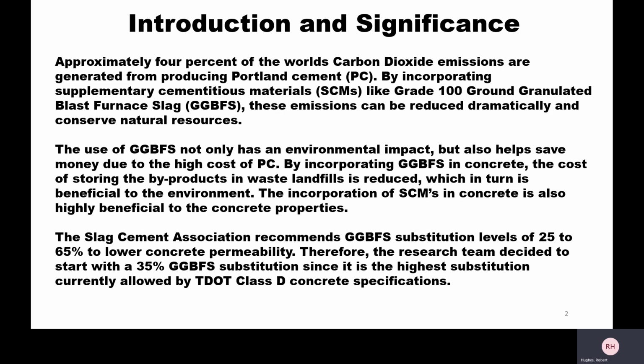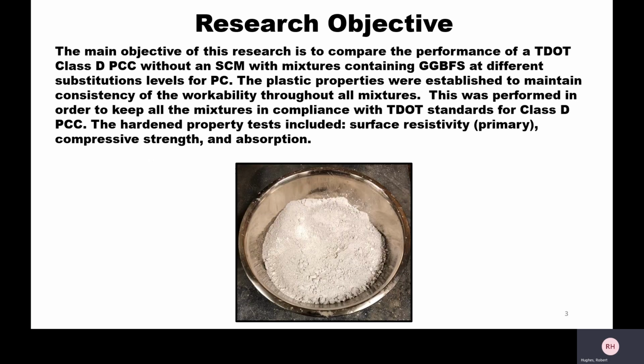Knowing this, the research team decided to start with a 35% substitution, since it's the highest substitution currently allowed by TDOT Class D concrete specs. The main objective of this research is to compare the performance of a TDOT Class D concrete without an SCM to mixtures containing GGBFS at different substitution levels for Portland cement. The plastic properties were established to maintain consistency of the workability throughout all these mixes. This was performed in order to keep all the mixes in compliance with TDOT Class D specs. The hardened property tests include surface resistivity, SR, compressive strength, and absorption.